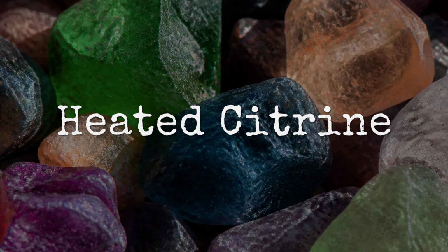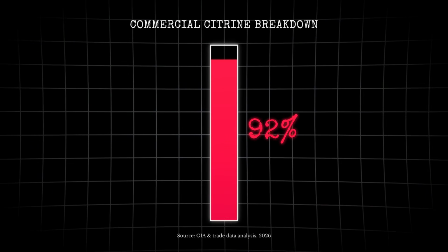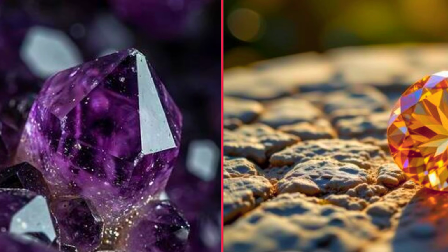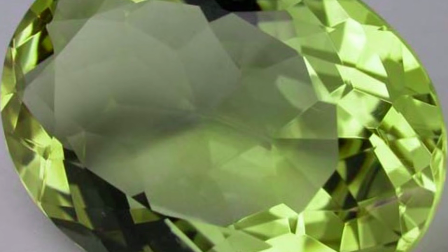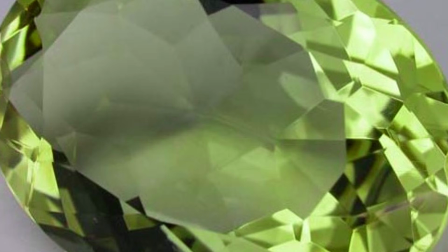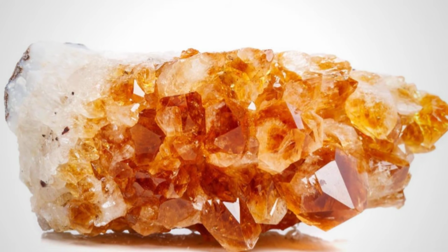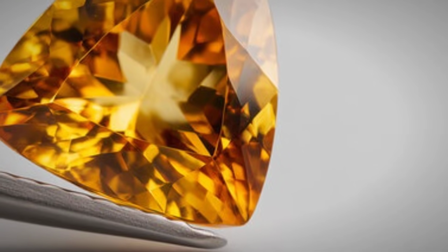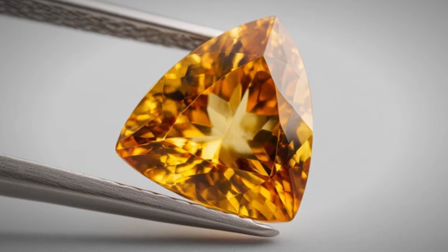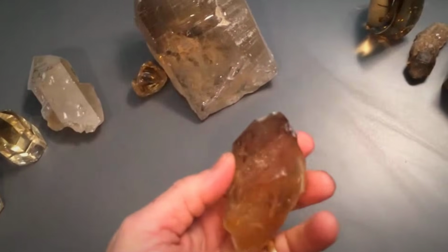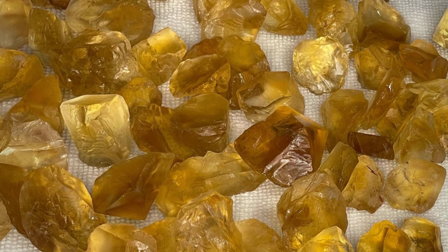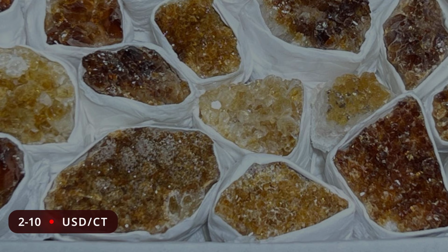Heated citrine. 95% of commercial citrine started life as purple amethyst, heated to between 470 and 560 degrees Celsius until the iron impurities shift from purple to orange. Natural citrine is pale, smoky yellow and genuinely rare. Heated amethyst turns a burnt orange-brown that natural citrine never shows. The telltale sign is a white base, visible through the table facet, a remnant of the original amethyst color zoning. If the color looks too saturated or too uniform, it is almost certainly treated. Retail for heated citrine, $2 to $10 per carat. Natural citrine, $10 to $30 per carat. And good luck finding verified specimens.